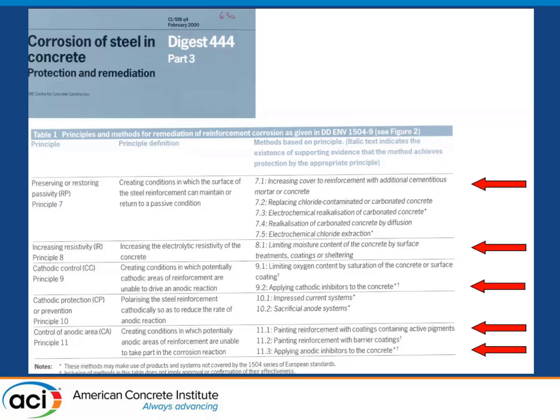And on this job, when I think about the specifications and the products that were used, they applied 5 of these principles to the job. They increased cover through the use of polymer modified materials and effective cover. They limited moisture ingress through the use of coatings. They used a surface applied corrosion inhibitor that was anodic. It was an anodic inhibitor as well as cathodic. And they used a rebar coating as well to, again, give effective cover to that steel, which a lot of it had insufficient cover that they were really trying to deal with.